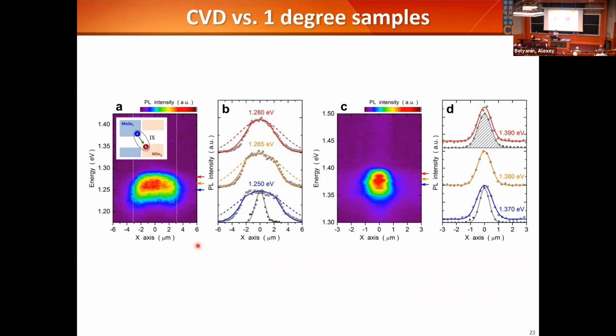So what we found is that in the CVD sample, the excitons can indeed move. And in this particular data, they're clipped by the boundary of the layers. So they're not huge, they're a few nanometers, a few microns.